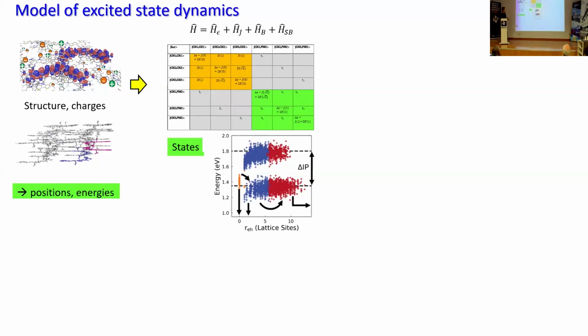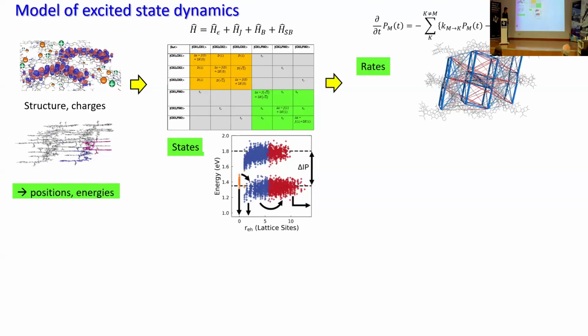Once we know the positions, we can work out the couplings between different molecules. Then we can solve that Hamiltonian to find the energies of the states. We can also look at the character of the states. Some of the states are excitonic, and then some of the states will have charge transfer character. We can then classify them in terms of excitonic, charge transfer, and charge separated states.